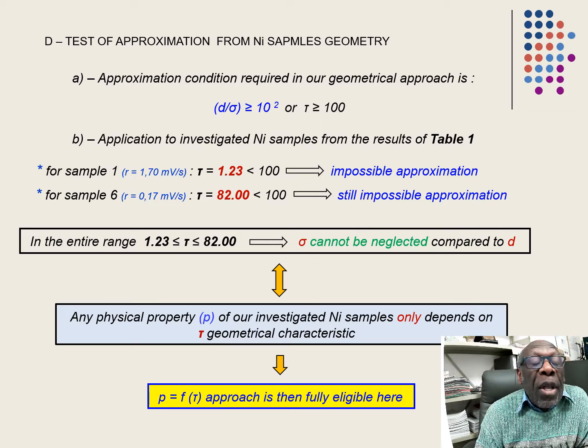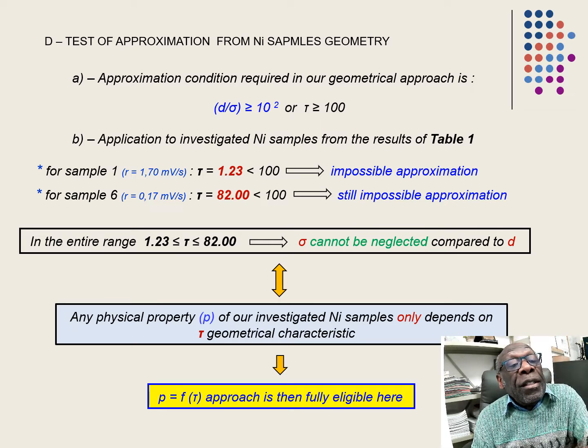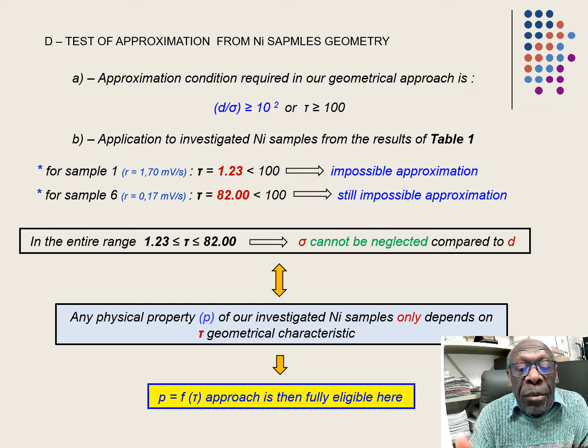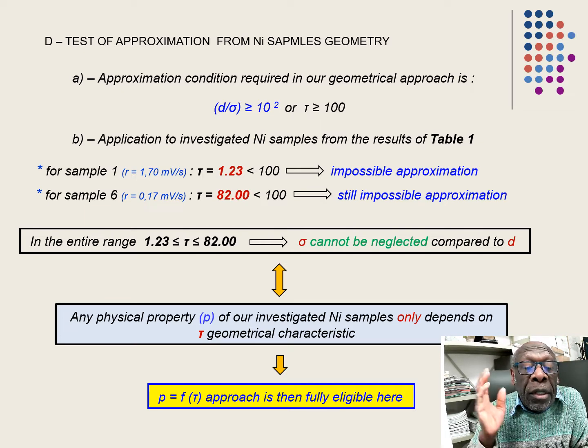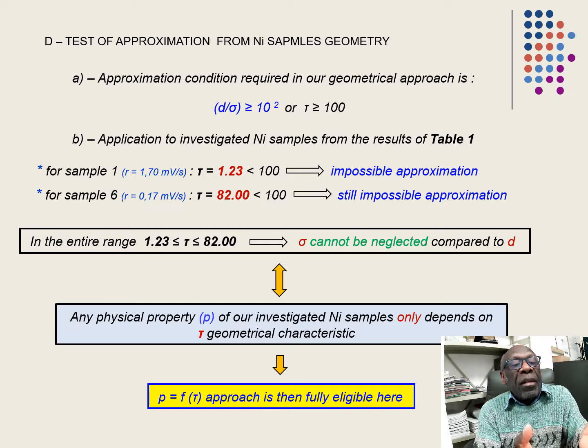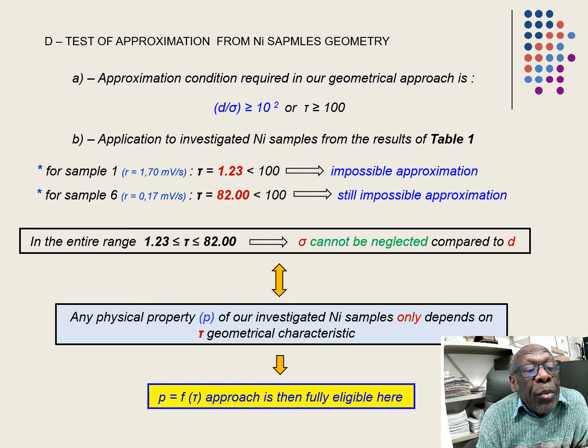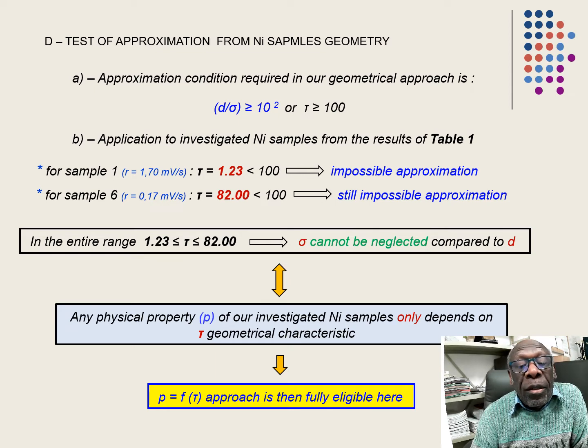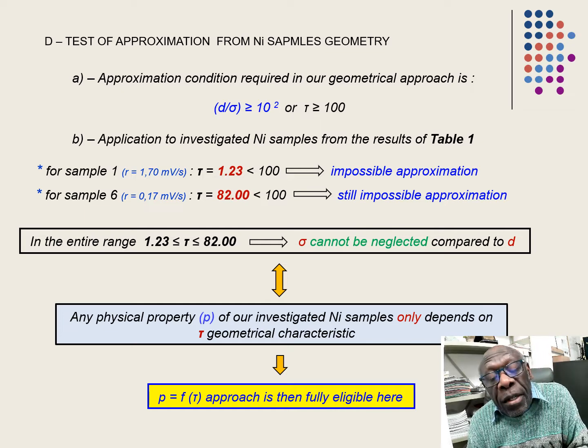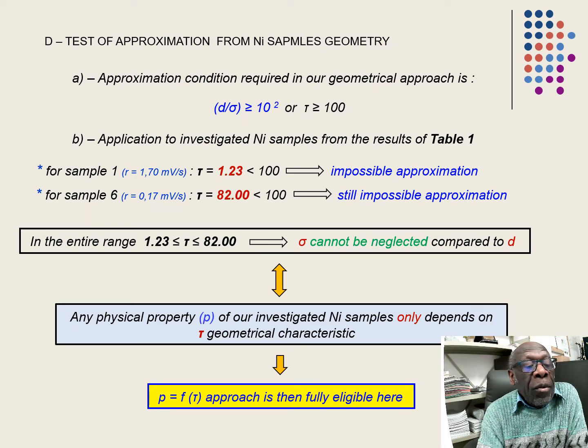But before studying the property of the films, it's better to examine the approximation possibility. The condition is given here, tau superior or equal to 100. Applied to our nickel samples, you can see that the two limits in the value of tau lead both of them to the impossible approximation. That means that in our case, sigma cannot be neglected compared to d for all of our samples. That means that you cannot study the evolution of the film property using d variable. You should, of course, use tau variable, where the p versus tau approach is here fully eligible.